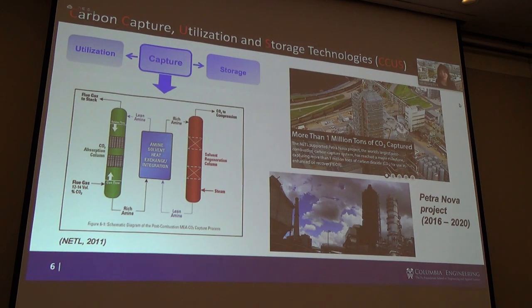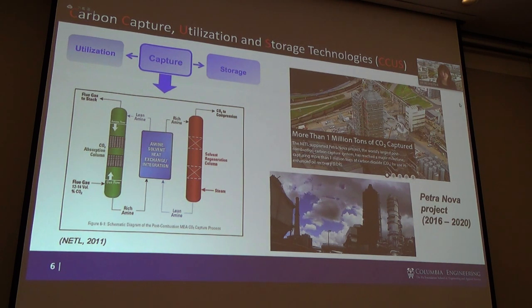If you look at the left-hand side, this is how liquid solvents like monoethanolamine or any amine-based liquid solvents would capture CO2. We capture CO2 at lower temperature, and we add energy by heating up the reactor to higher temperature to regenerate the liquid solvents. And ultimately, these liquid solvents have to last many hundreds and thousands and 10,000s of cycles for sure to be economical and also make sense for the life cycle analysis of the material system.